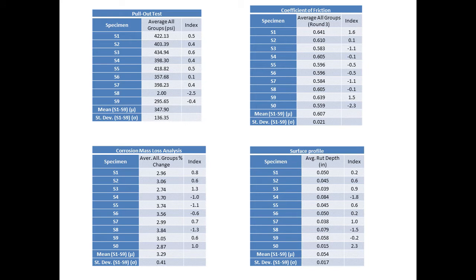In terms of corrosion: if you apply TPOs on chloride-contaminated concrete, that is not a corrosion protection measure—you are not going to get much benefit. If the concrete is chloride-contaminated, you may still want to use TPOs for friction, as they will maintain friction for the given life expectancy of a TPO. But in terms of corrosion protection, applying TPO on chloride-contaminated concrete will not help.